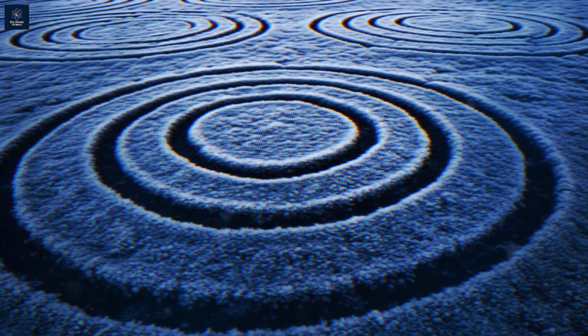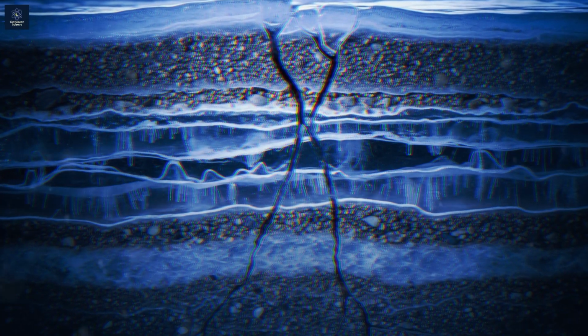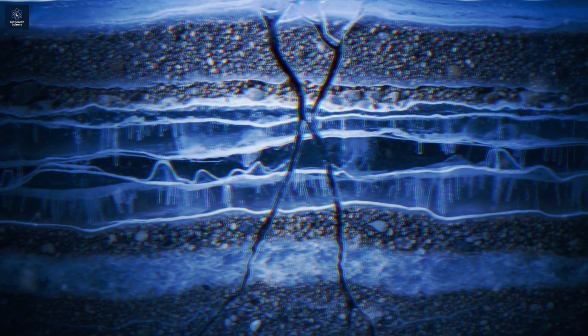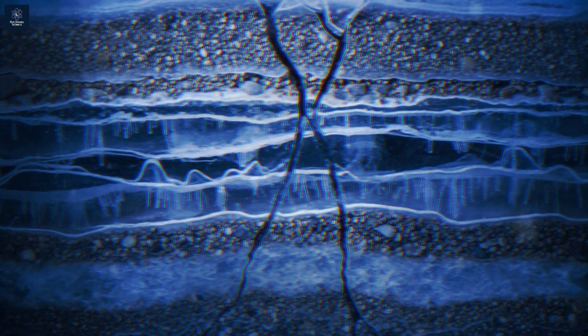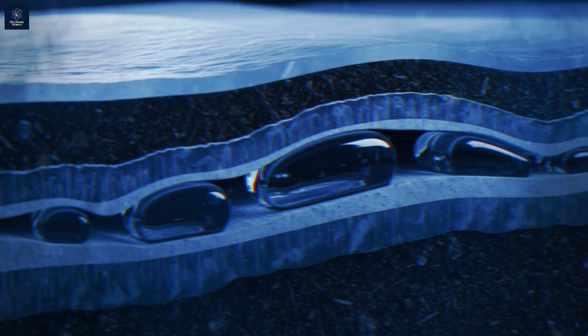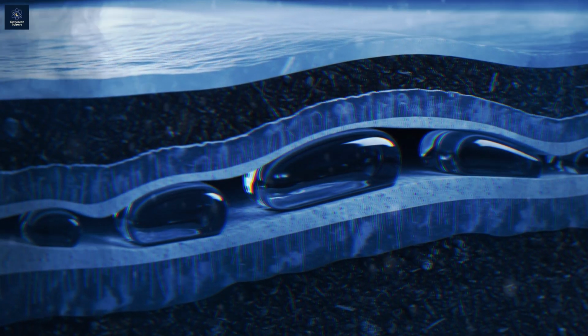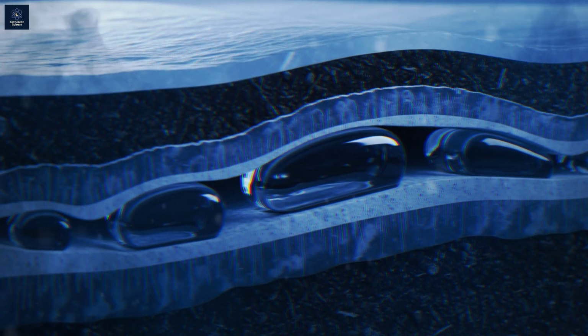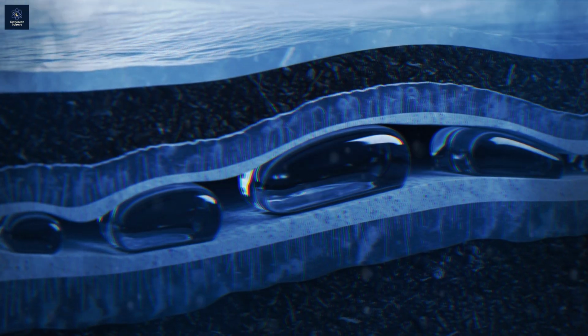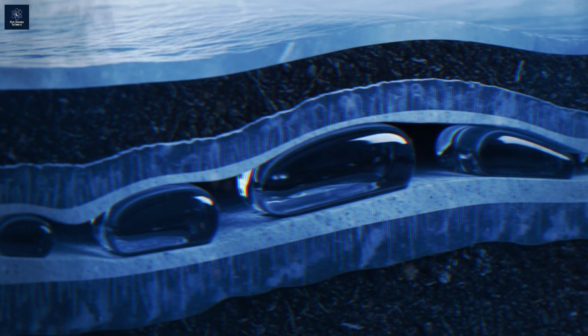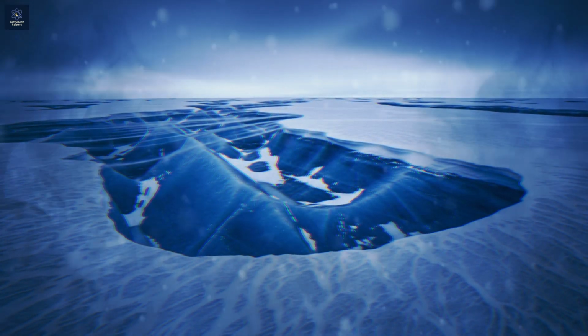Glaciers that contain liquid water, even tiny amounts distributed along grain boundaries or concentrated at the base, flow notably faster than completely frozen glaciers. Recent laboratory experiments revealed something surprising about temperate ice. Ice containing small percentages of liquid water deforms almost linearly with stress, quite different from the nonlinear behavior of cold ice. This helps explain why some ice sheets can accelerate suddenly when surface meltwater reaches the glacier bed through cracks and channels. The presence of even 1% liquid water by volume can increase flow rates by factors of 10 or more. Water is ice's lubricant at the molecular scale.